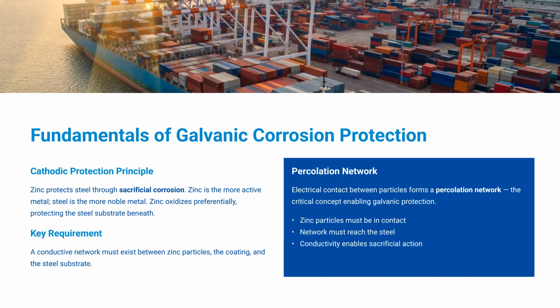To understand the difference between zinc dust and zinc flake systems, it is important to briefly review the principle of galvanic corrosion protection. Zinc is more electrochemically active than steel. This means zinc will corrode preferentially, sacrificing itself to protect the steel substrate beneath. For this sacrificial protection to work, there must be an electrically conductive pathway connecting the zinc particles to each other and ultimately to the steel surface. This interconnected conductive structure is known as the percolation network. Without sufficient particle-to-particle contact, the so-called percolation threshold, galvanic protection cannot occur effectively.